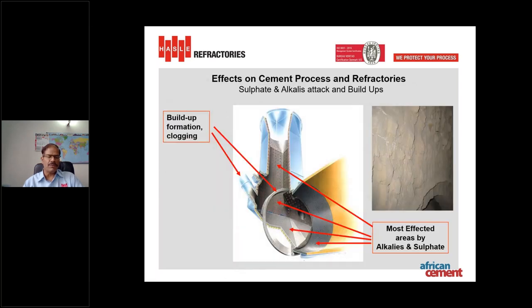So what happens when we use these alternative fuels? The sulfates, alkalis, and chlorides actually cause buildup and coating in the main working areas of the cement plant. There is too much coating formation in the smoke chamber area, riser area, feed pipes, and also in the cyclone cone and cyclone roof area.